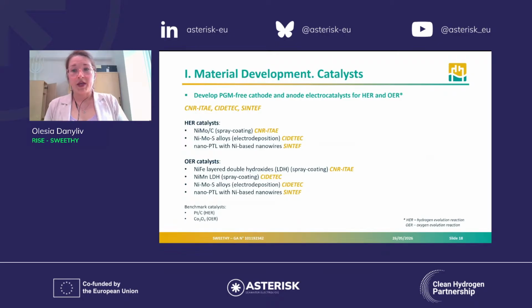These are the PGM-free catalysts that were chosen for this project. On the cathode level, it's nickel and molybdenum carbon catalyst made by spray coating, nickel and molybdenum sulfur alloys made by electrodeposition method, and nano-PTLs with nickel-based nanowires. For the anode catalysts, we also test the last 2 catalysts that I mentioned, but we also synthesize the nickel and iron and nickel and manganese layered double hydroxide. We also chose the benchmark materials, platinum for cathode and cobalt oxide for anode.